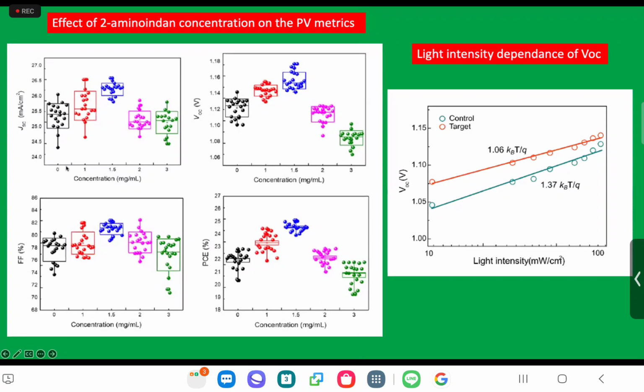Here we show that it depends on how much you add to the starting solution. 1.5 milligram per milliliter, that's very little, but that gives you the best performance. And the PCE for that PIN structure is high, at least it was at the time when this paper was published. What also looks very nice is the ideality factor close to 1. That tells you that you can get a very good fill factor, and you get a fill factor over 80%.